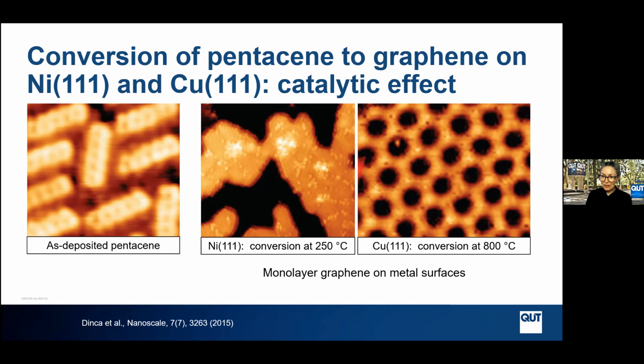What we did here was to convert pentacene into graphene on two different substrates, either on nickel 111 or copper 111, where you see the moire pattern associated with the graphene growth. What you'll notice, of course, is the very different reaction temperatures for the highly catalytic nickel surface versus the moderately catalytic copper surface. In both cases, what we were needing to do here was CH bond breaking and then carbon-carbon bond formation between these activated fragments.